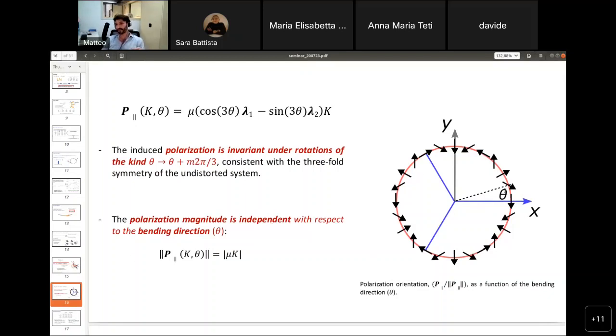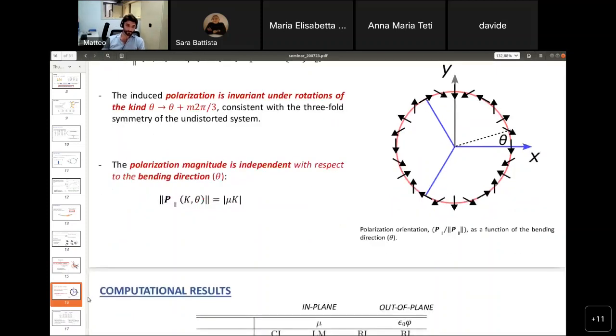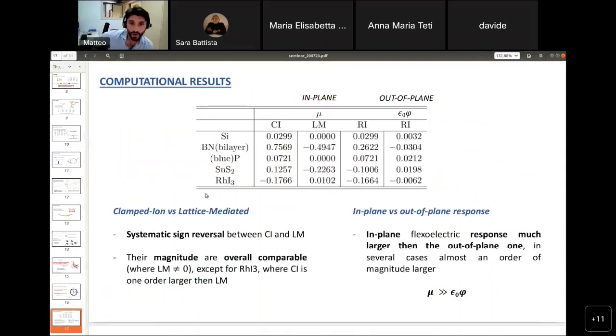Here at the side, we can see indeed the behavior of the polarization while changing the angle theta, the direction of the bending. Again, we can look at the comparison between the clamped-ion and lattice-mediated effects, where we find that first of all there is a systematic sign reversal between the clamped-ion and lattice-mediated effects, and in addition, similar to the previous case, that is the out-of-plane response, we find that their magnitudes are overall comparable, except, for example, in the case of rhodium triiodide, where the clamped-ion response is one order larger than the lattice-mediated effect.